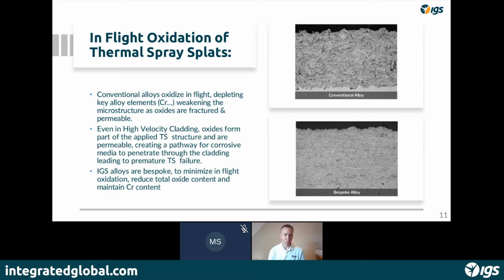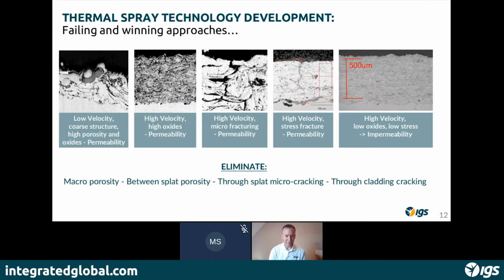So with IGS, we don't use conventional alloys. We've developed bespoke alloys where we're ensuring that the alloy constituents are consistent once it's been applied onto the surface. So elements such as chromium, which readily oxidize in the air, we have to manage that element to make sure that once it's applied, we still have sufficient levels of chromium to give us that same resistance to pitting that we need to perform. IGS are a thermal spray company.